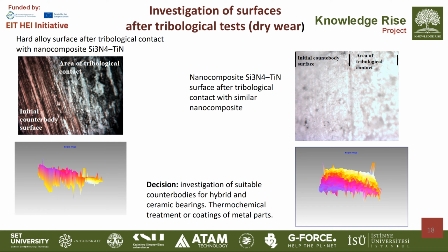The initial surface appears relatively smooth, but after the test, the area of tribological contact exhibits pronounced wear tracks and plastic deformation. The corresponding 3D surface topography at bottom left confirms significant surface roughening and material loss due to adhesion and abrasion. On the surface, in the area of tribological contact, a special layer formed which contained not only hard alloy but the debris of ceramic, nanoceramic, and it decreases in the future the wear of the system and the friction coefficient.